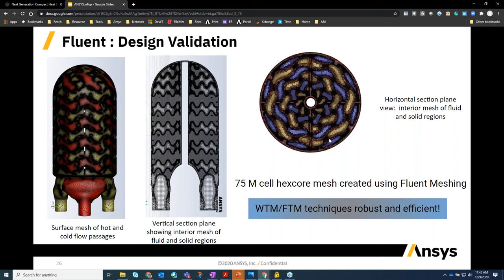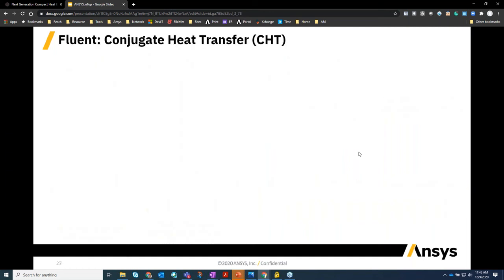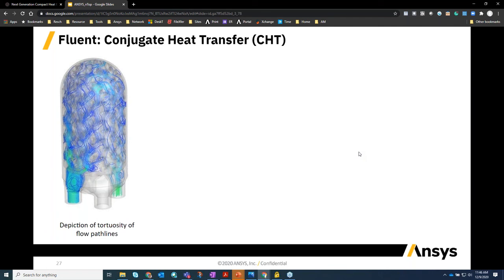And the cross section over here on the top right shows the hot and the cold zone, and you'll see the solid zone, which is kind of this orange-gray region. So all those zones were meshed properly. And so what does this mean for results? First things first, this was, like I said, about 75 million cells. It took about 2 hours on 196 cores, I think, with this turbulent flow simulation using a RANS depiction, which is a realizable k-epsilon type of model.